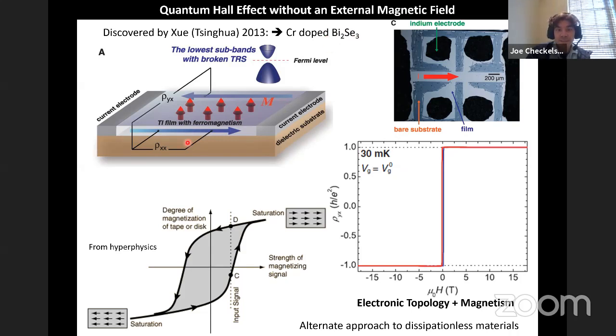And what they found in this system was when they measured the electrical transport at very low temperature, just like that graph I showed you from Wikipedia with a quantized Hall response, they also saw a quantum Hall effect. But instead of being that kind of staircase driven by an external magnetic field, now it looked like a ferromagnetic hysteresis loop, because the quantization was responding to the ferromagnetism associated with these chromium ions. It was a fantastic achievement, which demonstrated to the field that you could combine these two extremely rich areas of condensed matter physics, magnetism and quantum Hall physics, into one animal.